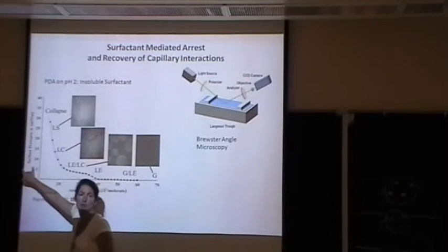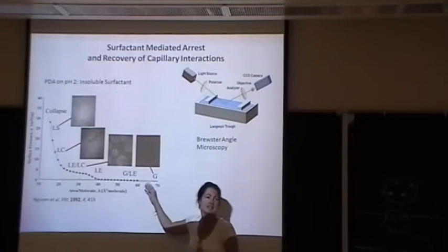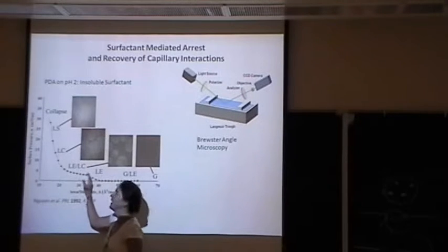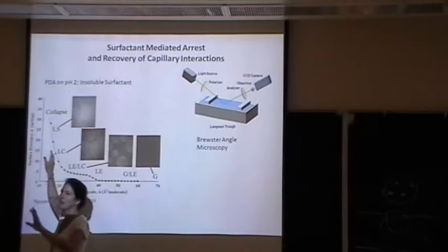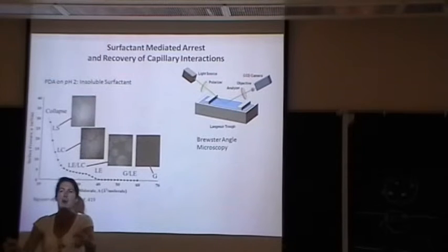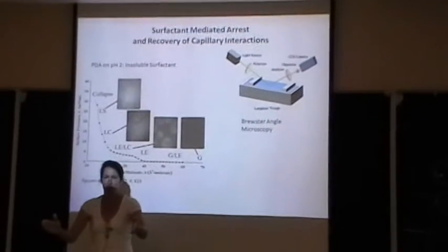You can compress that thing, and it will be in expanded regions. This is the surface pressure, the surface tension reduction, versus the area per molecule. In the expanded region, it's in a gaseous state. Then it will go through a two-phase coexistence and go up into a liquid state. Then it will go through two-phase coexistence and go into another state. And still, we weren't satisfied. We compressed further, and it goes into another state. And then we compressed further. It started to pop out, make little crystals. We have squeezed the heck out of this monolayer. This is rather an extreme situation for a surfactant layer. And then we did that, squeezing with some particles in the surface.